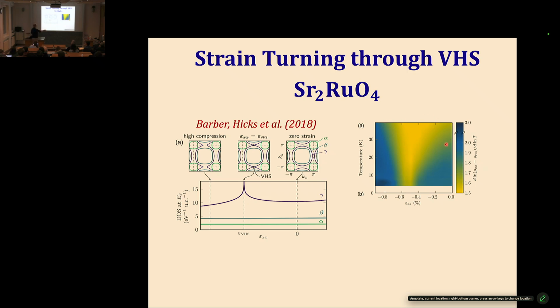And just seeing this behavior is what you associate with a quantum critical point. That means that you vary some non-thermal parameter in the system, and at zero temperature, there's some transition between two qualitatively different states in the system. In this system, we know that there's nothing exotic going on. There is a quantum critical point, but a very boring one. It's just a change in the connectivity of the Fermi surface, and that's sufficient to give us this fan-shaped behavior.